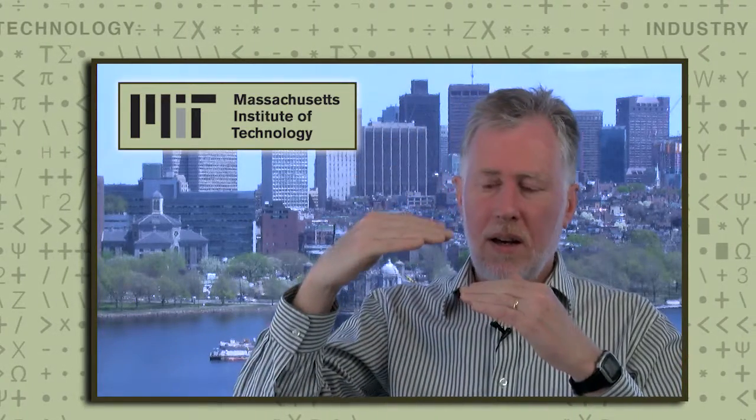To actually access the direct bandgap of germanium, we had to do two things. We had to strain the material, and we had to highly dope it. These two things allow you to push the indirect and direct bandgap close enough so that you get a spillover of electrons from the indirect bandgap into the direct bandgap. And then you open this recombination path that will give you the light emission.